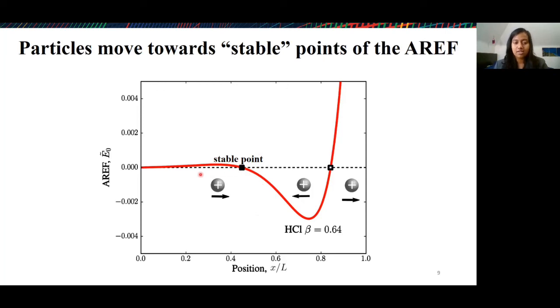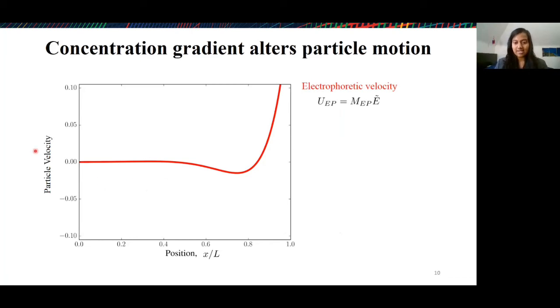Now, what we also found, though, is that particle motion under an electric field alone does not completely describe particle motion in these systems. And so let's see the reason for that. Let's look at a slightly different plot, which is that of particle velocity against position. Here, the red line is the electrophoretic velocity, which is particle motion under the electric field E. But in these systems, in addition to an electric field, we also have a concentration gradient. So charged particles in a concentration gradient undergo diffusiophoresis, where the diffusiophoretic velocity is proportional to the gradient of the concentration. And it looks like this gray line on this plot.